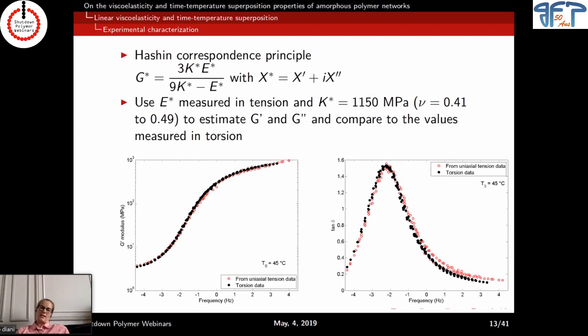So what does it mean? That means that those tests are completely equivalent. You can characterize the linear viscoelasticity in uniaxial tension or in torsion or shearing. And if you wanted to have access, for example, to the Poisson ratio or bulk modulus viscoelasticity by running both experiments, your experiments are not sensitive enough to do that. So you won't have access to the viscoelasticity of incompressibility.